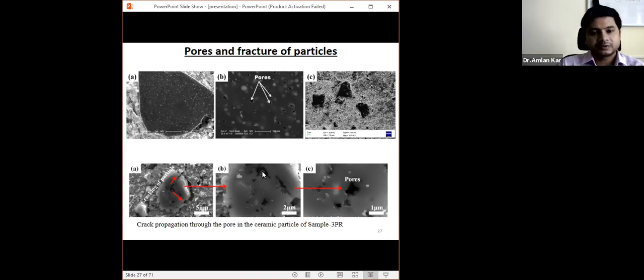And during the deformation process, since friction stir processing is a high strain deformation process, whatever crack has developed inside the particle actually propagates further. And because of the propagation of the crack, the individual layer is subjected to fragmentation. And because of the fragmentation, you can see that smaller grain size, smaller particles are also found in the composite material. Okay.